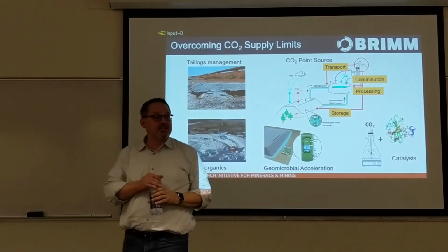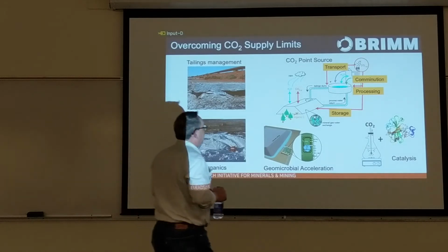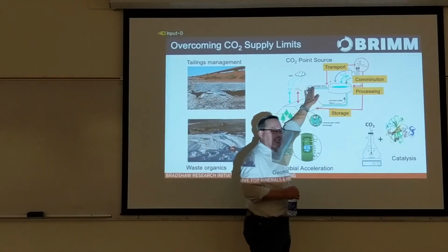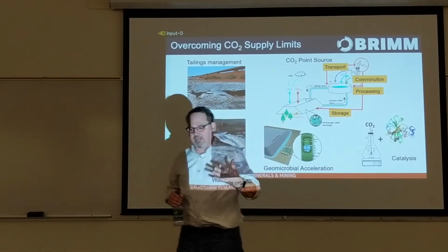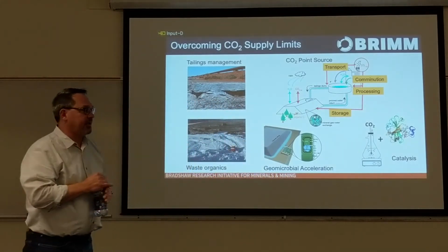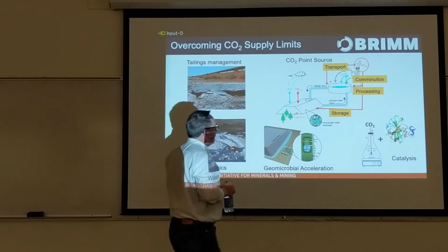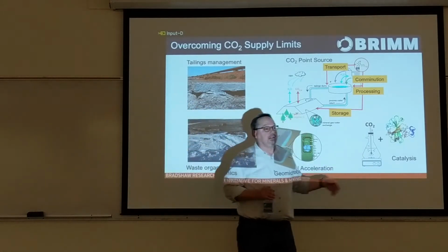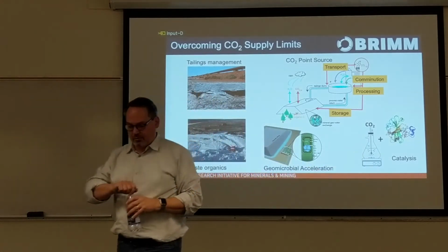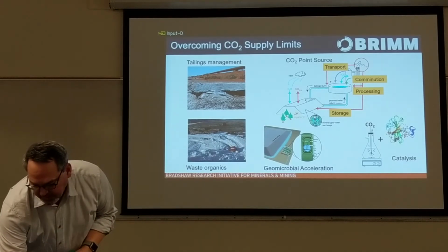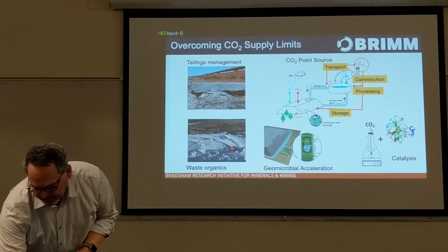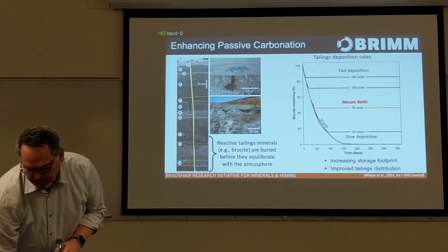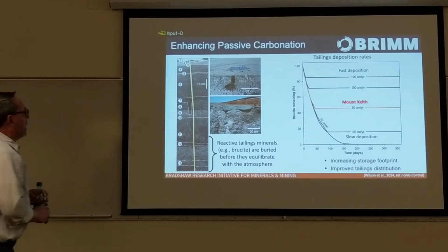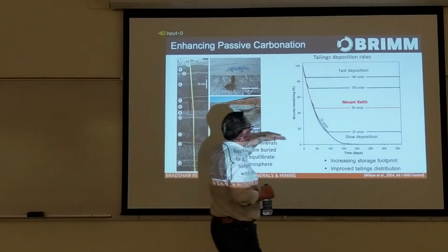This is a 20-minute residence time in the tailings pipeline at Mount Keith, for example, so we have essentially a nice turbulent flow reactor we can use, or we could inject CO2 into the tailings pipeline. So there's a bunch of different ways you might supply CO2. We can use catalysts to accelerate the absorption of CO2, the hydration of CO2 in water. So for Mount Keith, for example, essentially this is what's currently happening.